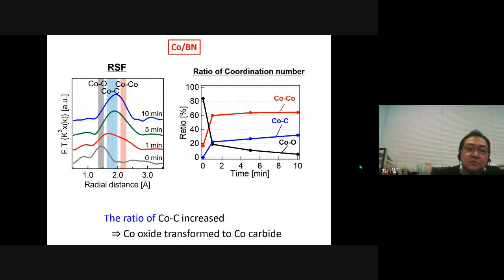The left figure shows RSF during single-wall carbon nanotube growth. After ethanol supply, the dominant peak shifted to the cobalt-carbon position. This indicates formation of cobalt carbides. To investigate the chemical state in more detail, we estimated coordination numbers of cobalt-carbon and cobalt-oxygen bonds by the curve fitting of RSF.